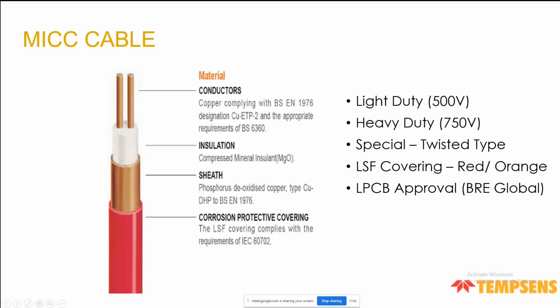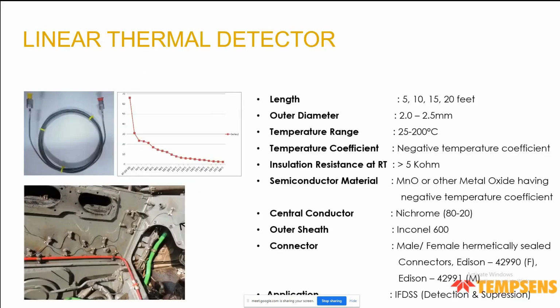These are mineral insulated copper cables used for critical areas for power. They are long length cables with an outer sheathing of copper, or they can also be with a special outer sheathing for corrosion protection. These cables we have supplied to some of the plants, and they have LPCB approval. Even after 8 hours of burning at 800 degrees centigrade, the connection would still be there. For those critical areas, such cable can be used.